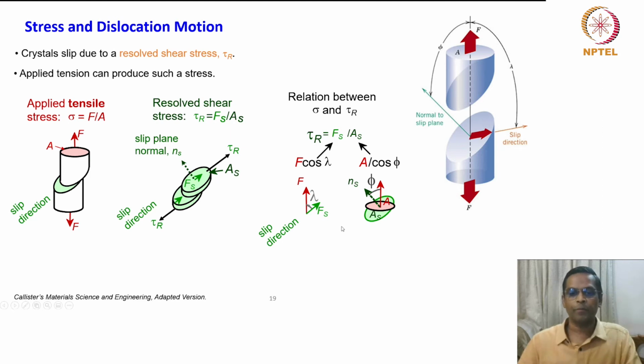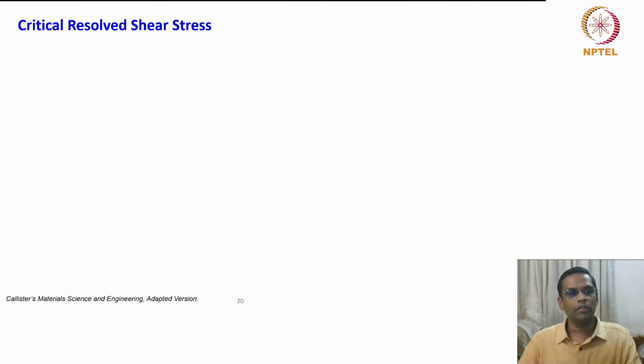So if you look at these substitutions, what you will see here is tau R is equal to sigma cos lambda cos phi. So that is the relation you get between sigma and tau R. So this is a fundamental requirement for the slip to take place. Okay. It is not that a resolved shear stress of any quantity will cause slip. There is something called critical resolved shear stress.